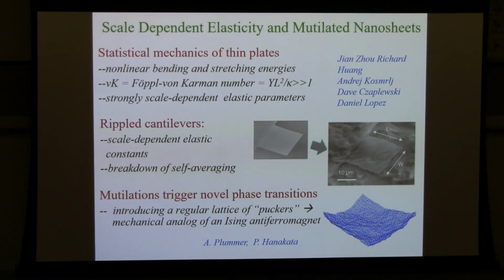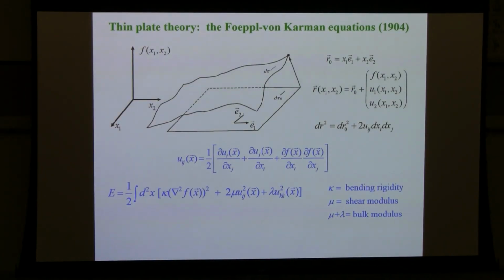Okay, so here's a recapitulation of a 120-year-old theory due to Foeppl and von Karman, and it's really pretty simple. It basically, if you think of it in solid-state physics language, you have in-plane phonons, U1 and U2, of this thin sheet that can escape into the third dimension if it wants to. And then you have an out-of-plane phonon field F that goes normal to this reference plane. So there are three phonon fields. This is a flexural phonon.